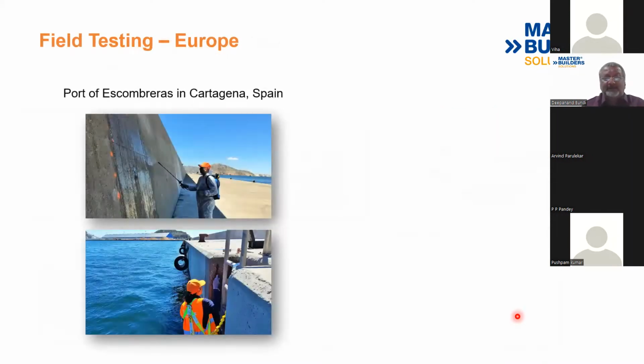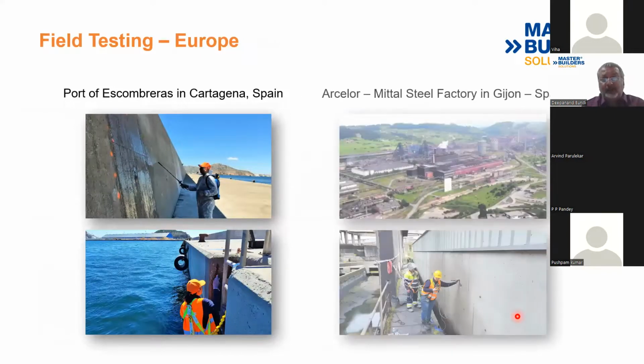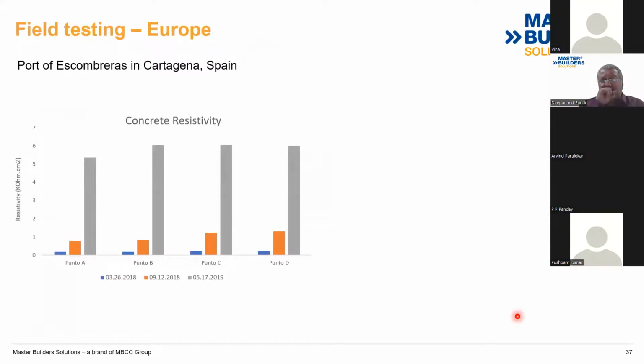In one of the ports in Spain, we did the application on the concrete surface which is exposed, and in Gijon in Spain, another ArcelorMittal factory, we did the application. In one of the ports, when we checked at the same point, there were 4 points on which the readings were taken. So if you look at the concrete resistivity, it drastically increased at all the 4 locations over a period of 1.5 years. This was done in 2018 and 2019. So at all 4 locations, the concrete resistivity increased in terms of protection.